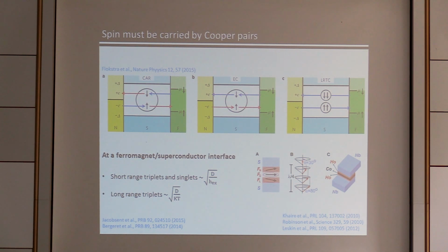Now, obviously, the first thing that seems strange is that while triplet pairs with a zero spin projection are created at the interface with the ferromagnet, they should not feel the action of the spin-orbit field at the opposite interface. And this is because the thickness of the niobium is larger than the coherence length. So they shouldn't feel the effect of this field and they shouldn't be rotated by it. However, now I have to say that this is a work in progress.